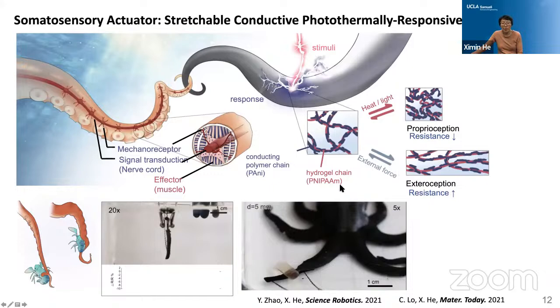At the same time, due to our unique synthesis method, the conducting polymer can be evenly percolated throughout this hydrogel network with a very uniform distribution, and reflect externally applied strain or deformation through the conductivity or resistance change. Therefore, upon the deformation or motion of this thermal responsive gel, the measured resistance will change. With this, we can back-calculate the deformation this material undergoes, to sense the strain and tell the system what deformation the material undergoes.